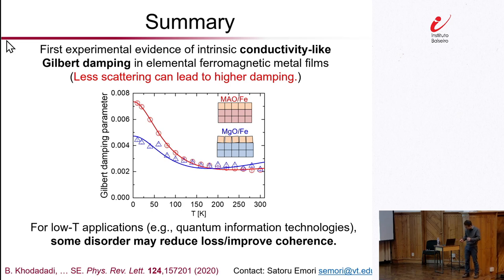So this tells us that if you want to minimize damping, reduce dissipation, it's actually better to not have an absolutely perfect magnetic material. It's actually likely much better to have a material with some amount of disorder. I find that to be interesting, and